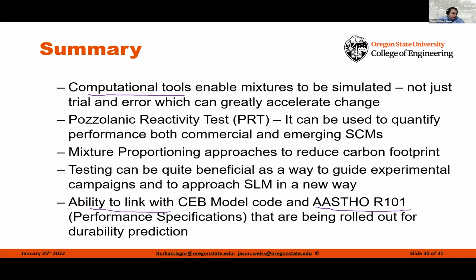So I'm not 100% sure I understand the question, but what we're using here is, Powers uses the water to cement ratio to predict things like the capillary and gel porosity. We're using the chemistry of the cement, the chemistry of the SCM, and the reactivity of these materials to directly predict the capillary and gel porosity. And then we're able to scale that up for several of these other predictions. Powers model is one that we'll use for strength, but we use other ones for transport properties or freeze-thaw. We use a lot of Fagerlund's work for freeze-thaw. We use a lot of reactive transport modeling for corrosion. So that's really where that direct link is made.